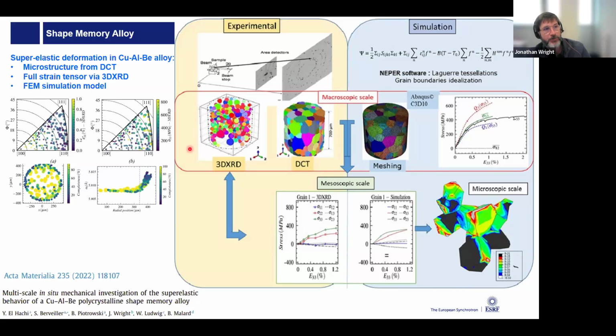So understanding how that works in detail, they've done this 3D XRD experiment where they measure all the diffraction angles. And from the diffraction angles, they have the grain orientations. They have something about the chemistry in the grains, and they have the stress and the strain tensors in the grains. And the sample is inside of a load frame. So as they apply load to the sample, they can see each single crystal, how it responds elastically. The diffraction contrast experiment, they can see the shapes of the grains, and they put all of this together with a finite element calculation to understand what really happens in the microstructure.